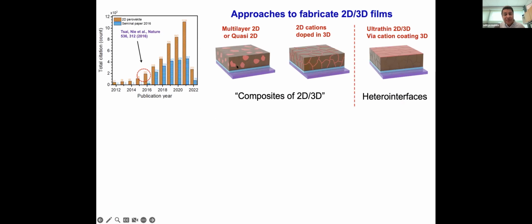And so there are different flavors of doing this. For example, what I call composites of 2D and 3D, where people take the 2D cations or 2D perovskites and mix them in a bulk phase in the 3D film, and spin coat it. This is often referred to as quasi-2D. Or they can take these 2D cations and dope them into a 3D film. And the thought here is that these organic cations end up in grain boundaries. Of course, very few reports actually demonstrate that these go to grain boundaries.